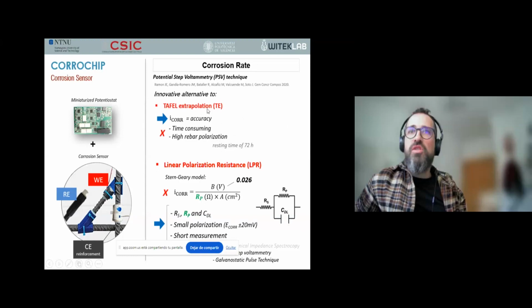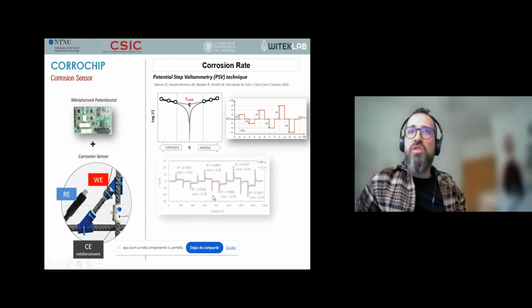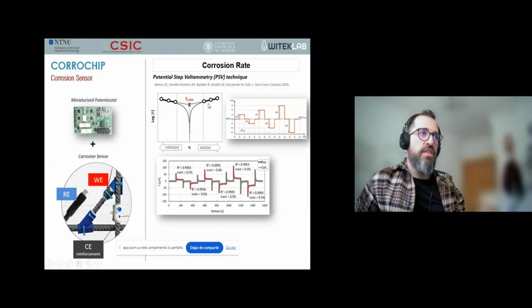So the new polarization technique, potential step voltammetry, used in Corrochip is designed to overcome the disadvantages of these classical techniques while retaining their main advantages. The PSV method is based on the Tafel method, and the corrosion current is obtained from the intersection of the Tafel lines. However, with PSV, each Tafel line is obtained through only 3 points. In this way, these are obtained much more quickly and, most importantly, without risk of producing irreversible polarization of the rebar. For this purpose, an alternating circuit of anodic and cathodic pulses of increasing amplitude is applied.